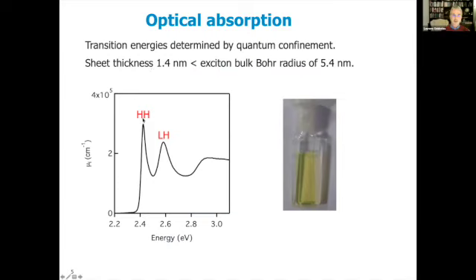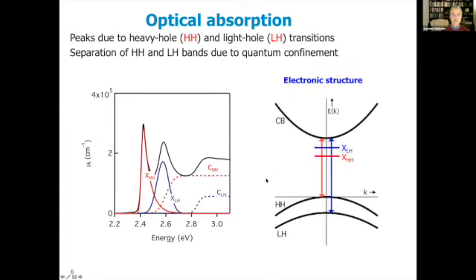quantum confinement, and it gives rise to these sharp peaks like you have in quantum dots, and then there is a continuum here due to excitation to higher lying states. Now, how do we interpret these spectra? So we have this first peak, a second peak, and then continua.